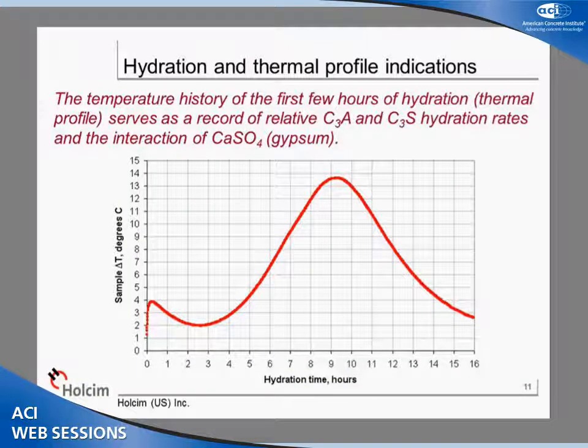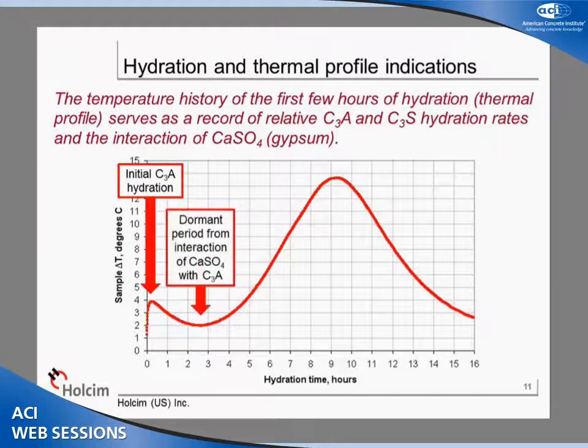Just a quick review of what happens in a thermal profile in order to see how we use this information and apply it to concrete mix performance. This is a changing state of temperature of a hydrating mixture over the first 16 hours in this case, very typical. The aluminates, the calcium aluminates in cement, fire off a lot of heat evolution immediately, which is then very rapidly controlled, if everything is ideal, by the interaction of calcium sulfate or gypsum in solution. And that provides us the delay period for finishing concrete and so forth.